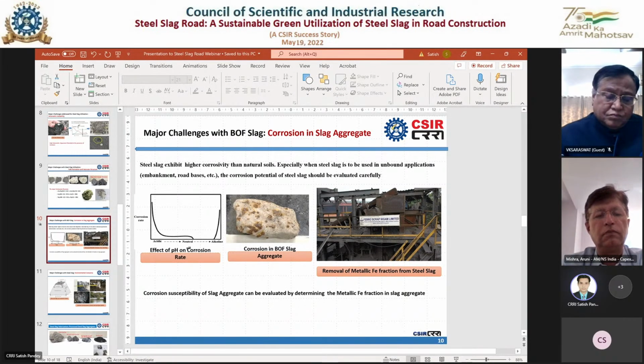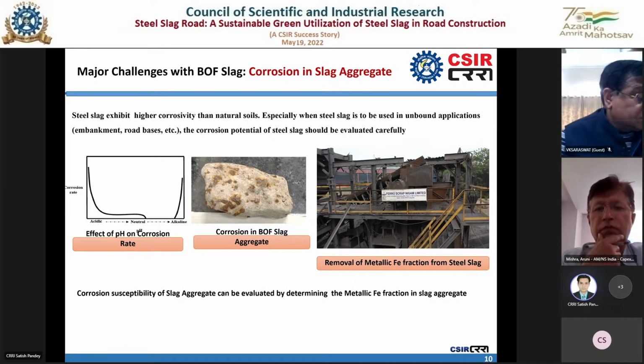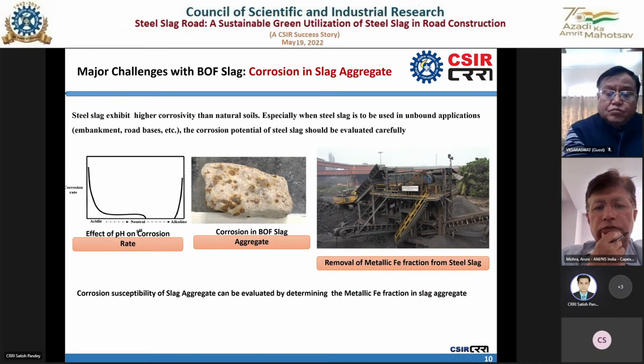The fourth important aspect is the chance of corrosion inside the pavement mass. In case slag is utilized for construction work, there may be a probability of corrosion on the steel slag aggregate surface. So we developed a customized process to reduce this corrosion by limiting the metallic iron presence inside the slag aggregate. Ideally, the metallic iron content inside the steel slag aggregate should not be greater than 3%. Accordingly, we set up the entire process in this FSNL plant situated at AMNS Hazira. It is a magnetic drum separation process. We customized the gauge setup inside this magnetic separation process so that it can effectively reduce the metallic iron content from the slag. And once it is less than 3%, it can be utilized without any issue for road construction.